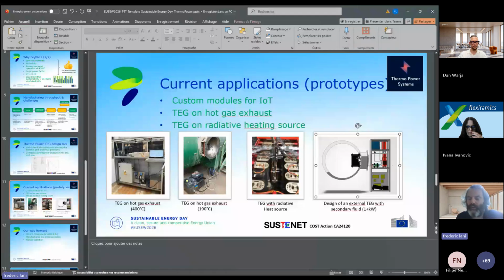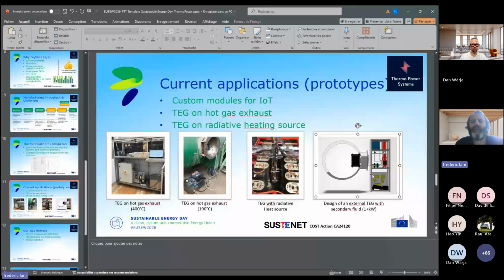What we demonstrated is that the return on investment is very short, and it's very profitable. If you compare to photovoltaic, at the end of the year, you have maybe 3-4% of global efficiency because of the insolation rate and things like that, but you capture only maybe 1/1,000,000th of the heat of the sun. So it's very low efficiency compared to the heat of the sun. In this case, with thermoelectrics, we are capturing only a fraction of available heat, and converting only a fraction of it.